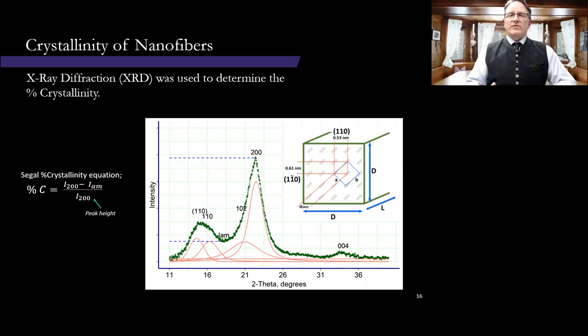Crystallinity is the other morphological aspect that's important, and we use X-ray diffraction to measure that. This test measures the scattering intensity of an X-ray beam from the nanofiber. The diffraction pattern produced here on the right is unique to the material, and from it we can determine the percent crystallinity using the Segal method. This is the equation here. It's the difference between the amorphous valley here and the peak of greatest intensity.